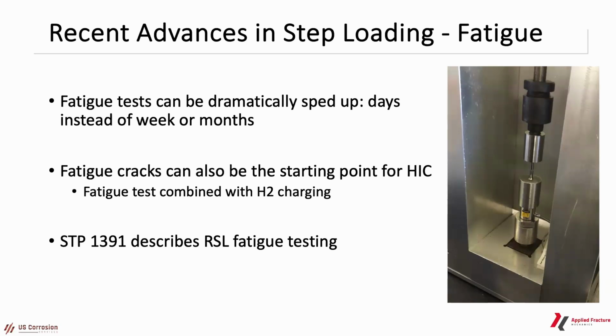One of the things that step loading can be helpful for is determining the initial threshold for fatigue cracking. So instead of just running a bunch of long fatigue tests and then looking at your data and going, okay, here's the point where our threshold is, we're doing step loading with fatigue so that we can determine a threshold and then focus in on that area more with more traditional step fatigue tests after that.